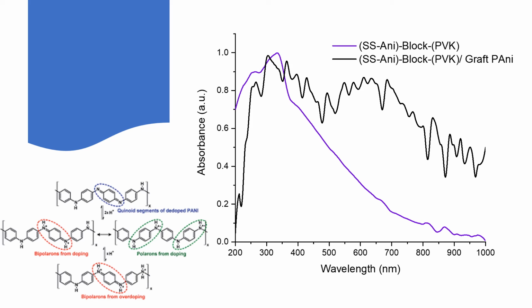Comparing the block copolymer with the ternary polymer in optical properties, we can observe that the ternary polymer presents a wide range of absorption that includes the UV region, visible region, and a part of the near-infrared region. This is because of the presence of the polyaniline chain in emeraldine salt state, which presents an equilibrium between polarons and bipolarons, which produce the conductive properties that polyaniline presents.